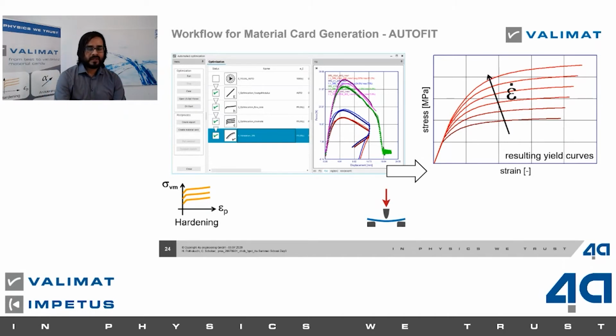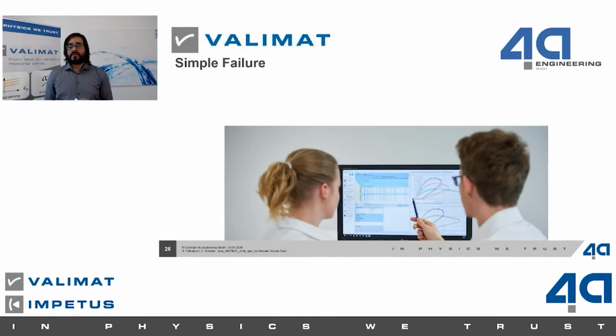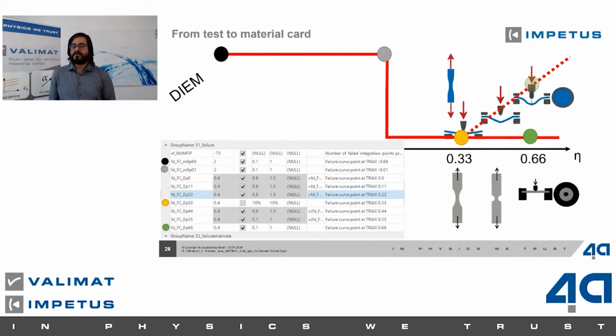After that, we looked at all our different validation results. We validated the generated material card with a puncture test, with a tension bending test, and with a tensile test. Then we set up simple failure based on the failure evaluation option in VALIMAT that takes into account the failure from the test data. So, a simple failure approach where we had a MAT_ADD_EROSION DIEM material model. We had no failure under compression and up from 0.33. So the complete tension side was set to one averaged value, where the failure strains were averaged out for all the different tests that were conducted.